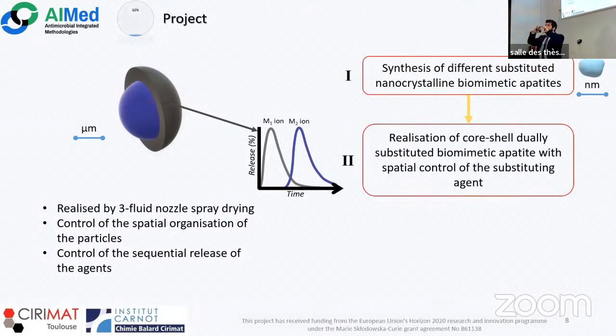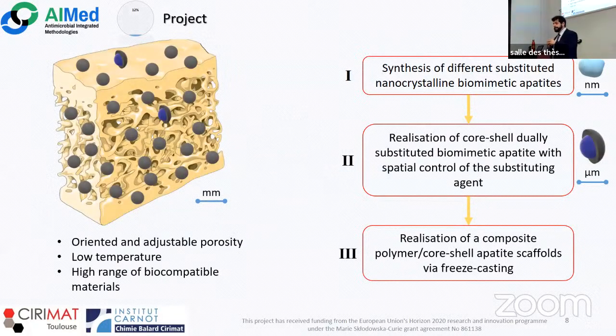Why that? Because by tailoring the structure of the particle, we look for the possibility, for example, to have first a strong antimicrobial action, and then the liberation of other ions that can enhance or help the growth of the bone. And then finally, we want to use these microparticles to produce a 3D composite scaffold using the freeze-casting technique. That is a technique that works at low temperature and that has a wide range of polymers that can be used, and of course biopolymers.